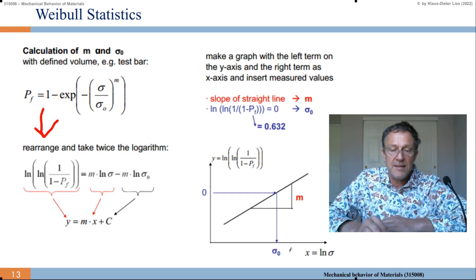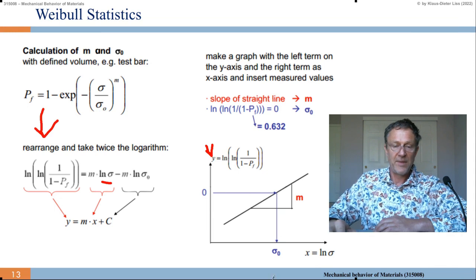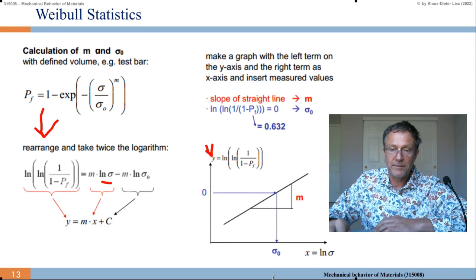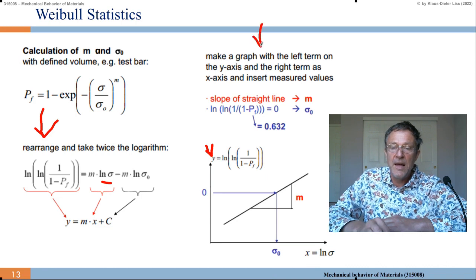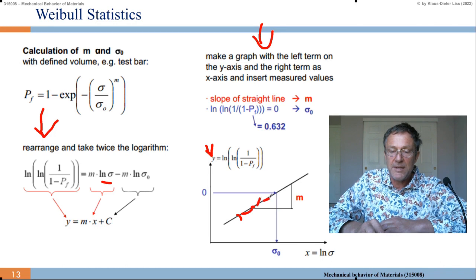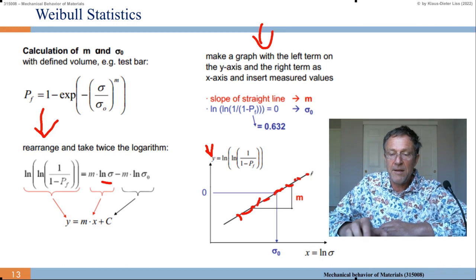So in this coordinate system where we plot the ln of ln 1 over 1 minus PF versus ln sigma, we get the slope m, so we get the Weibull modulus m. And we get the stress sigma 0. This is the axis offset in this graph. So we make the graph with the left term on the y-axis and the right term as the x-axis and insert the measured values. So you would make experiments and get values here, and then you fit the straight line.